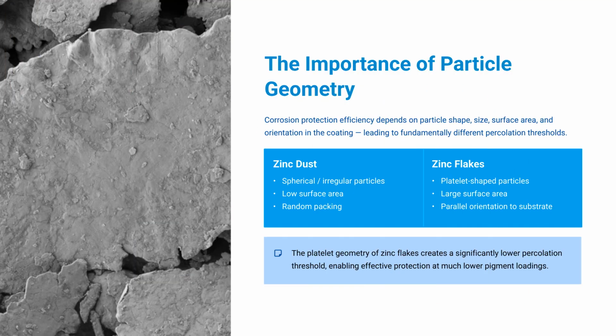One of the most important factors influencing the percolation threshold is particle geometry. Traditional zinc dust particles are spherical or irregular and pack randomly within the coating film. Their relatively low surface area means that high concentrations are necessary to achieve conductivity. In contrast, zinc flakes have a platelet-shaped structure with a very large surface area. During application, these flakes tend to orient themselves parallel to the substrate. This orientation creates significantly larger contact areas between particles, allowing conductive pathways to form much more efficiently. As a result, zinc flake systems achieve galvanic protection at much lower pigment loading levels.